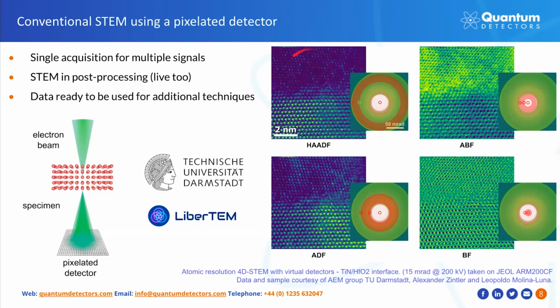The faint contrast from the titanium, which now suffers with the dynamic range of the screen, is also there, but we don't see it as well. But we could up the contrast on the top part. The annular dark field and annular bright field signals, on this diagonal, show more of the phase contrast information plus potential sample damage around the interface. The bright field contrast, as expected in here, is dominated by phase contrast signals.